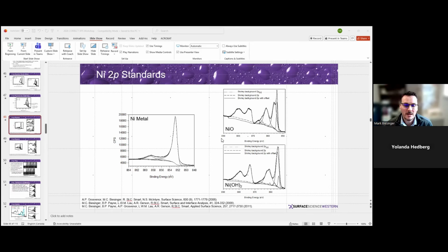Regarding the Shirley background in the nickel 2p 3/2 slide, why is there an offset applied? So again, if you look back here on this nickel slide, if I don't have an offset, this dotted line here will cut through, and you'll lose some of this area under here if you don't use an offset.